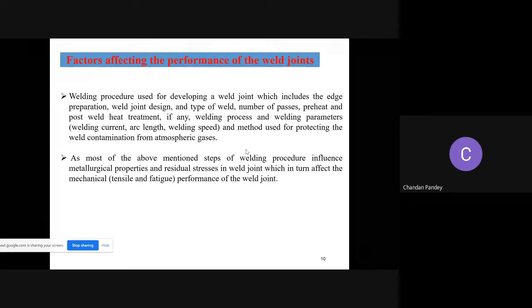If you talk about post-weld heat treatment, it means heat treatment that we perform just after welding, and that is not required for all types of material. Especially in the case of austenitic material, we don't need any post-weld heat treatment. But in the case of martensitic steel, after welding we get the formation of fresh martensite, and fresh martensite offers a higher amount of strength to the weld joint, but at the same time martensite offers poor impact toughness, meaning the energy absorbing capacity of the weld product will be less. That's why we perform post weld heat treatment in the case of martensitic steel.